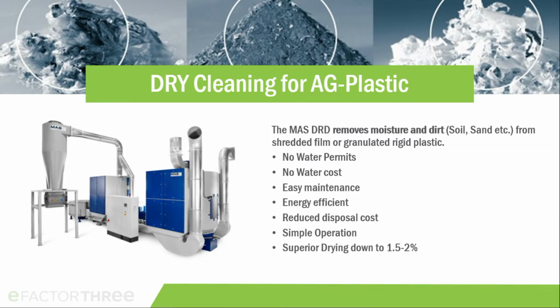This would be a shredded ag film, dirty. This is the dirt residual that we are pulling out. And this is the end product, the clean flake. With that, we take ag film from its 25% moisture and 30% dirt contamination to 1.5 to 2% moisture and less than 0.5% dirt contamination. It's fine dirt that's embedded in the structure of the film.